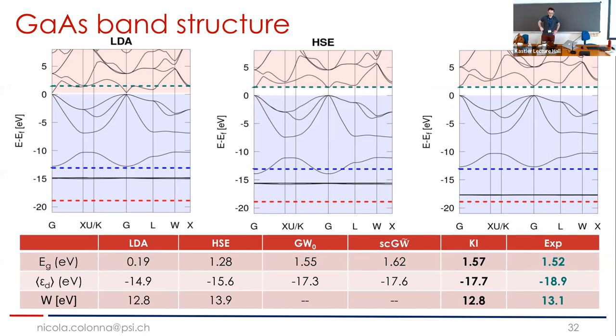The convergence is something we didn't check carefully, let's say. So in principle, the two have to converge in the very same way. The size of the supercell is exactly the same converging parameter as the number of k-points in your implementation. The screening coefficient should converge very, very easily in semiconductors. You don't need a very large k-mesh to converge an electric property like the macroscopic dielectric function. For metals, or when the gap goes...